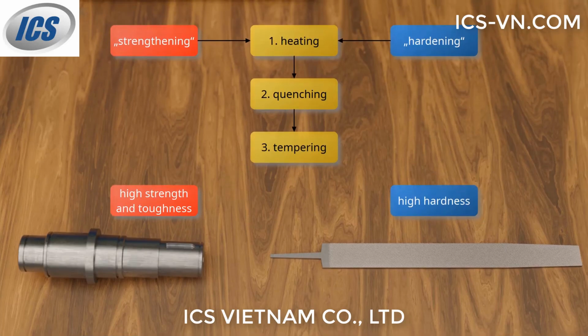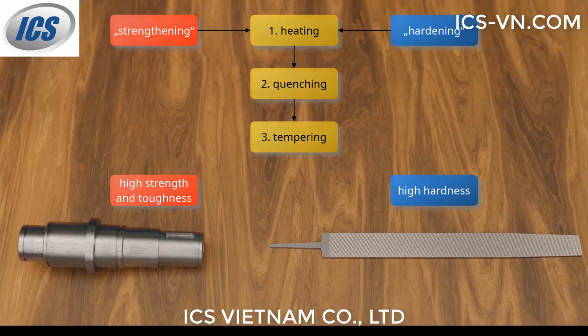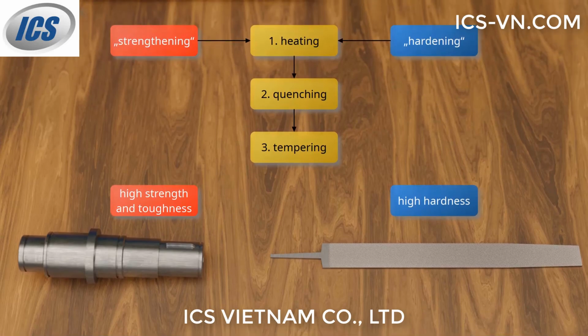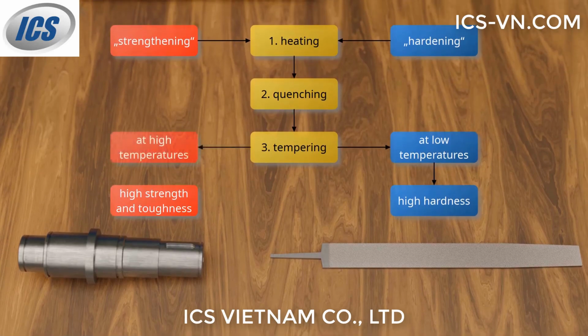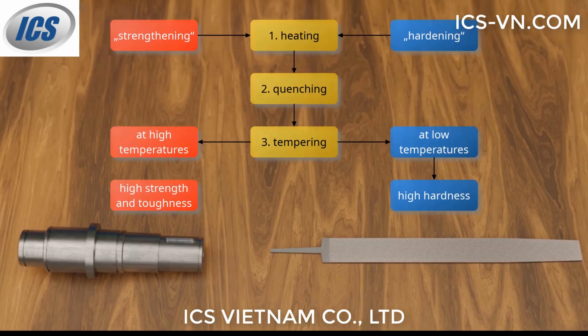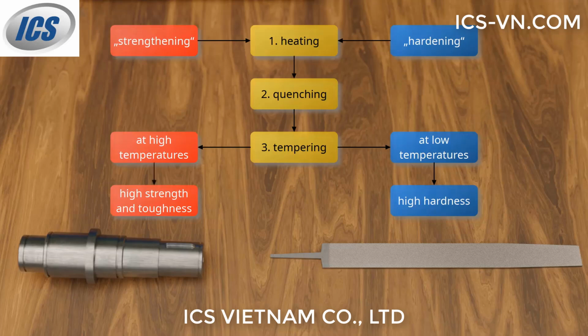Depending on whether the aim is to achieve high hardness or high strength with good toughness, tempering is carried out at different temperatures. If a steel is to be very hard, it is only tempered at relatively low temperatures in the range of 200 to 400 degrees Celsius, while at higher temperatures in the range of 550 to 700 degrees Celsius it becomes tougher and highly stress resistant.